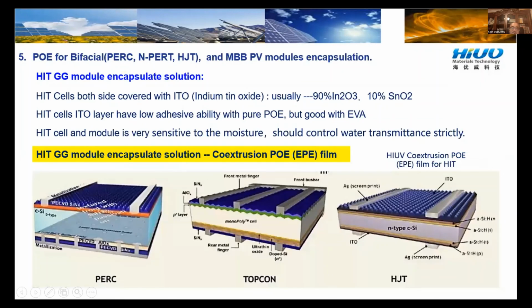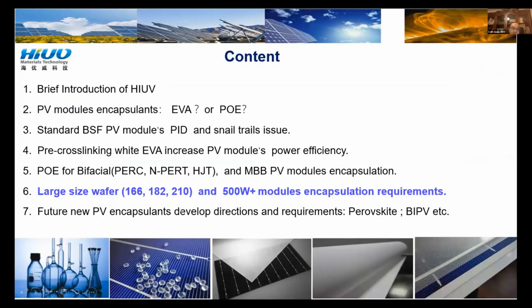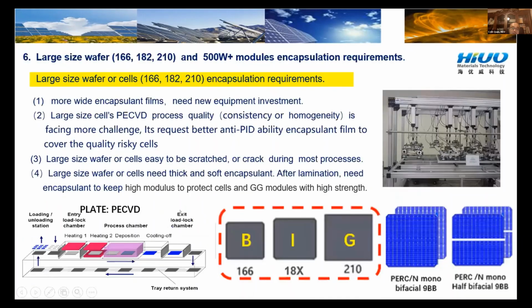Now the HIT cells are really sensitive to moisture and adhesive. Their adhesive ability is not so good, so co-extrusion will solve the problem better than polyolefin. And for the next 2 slides, for larger sizes we are still facing some anti-PID problems because of the equipment. They cannot achieve consistency or homogeneity of the PECVD level.